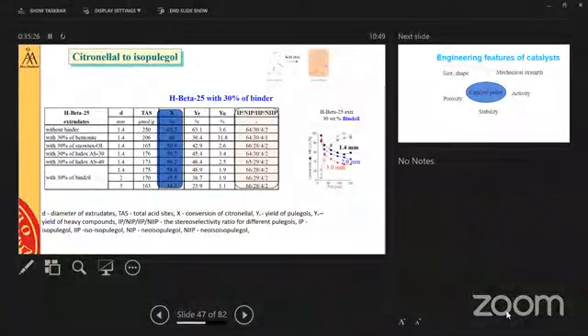What was important, and that's actually another important conclusion from the point of view of scaling up, is that the selectivity was not that much influenced by mass transfer. And this is actually an important conclusion, especially when we do scaling up in industry of reactions related to maybe fine chemicals or pharmaceuticals or fragrances, because there we are much more interested in selectivity rather than activity.